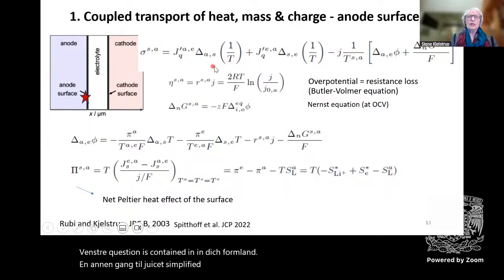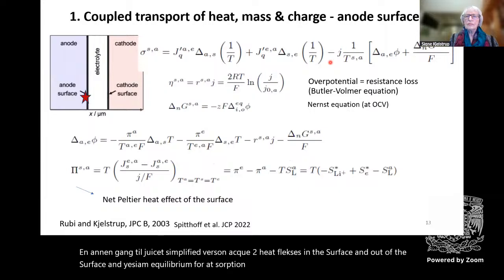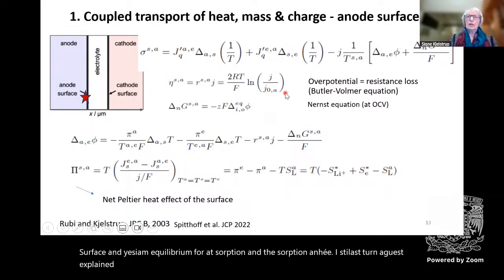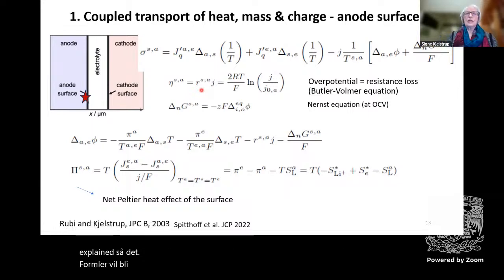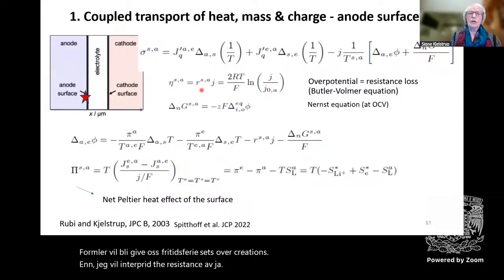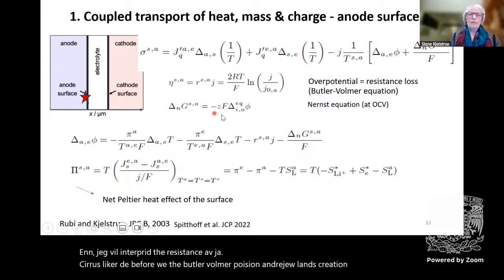I keep the two heat fluxes into the surface and out of the surface, and I assume equilibrium for adsorption and desorption. And here is the last term I just explained. So the formula will give us 3 times 3 sets of equations. And I will interpret the resistance of the surface like I did before with the Butler-Volmer equation. And here is now the Nernst equation for open circuit potential conditions.